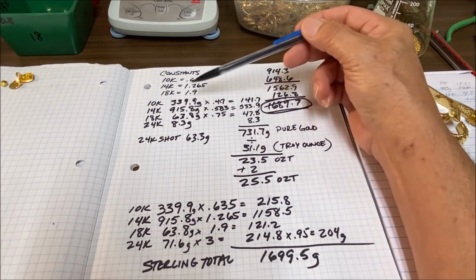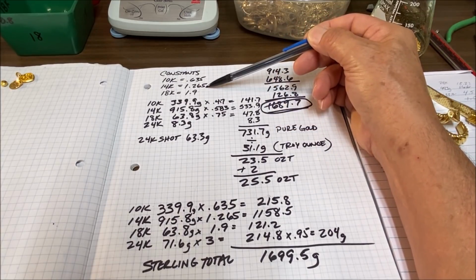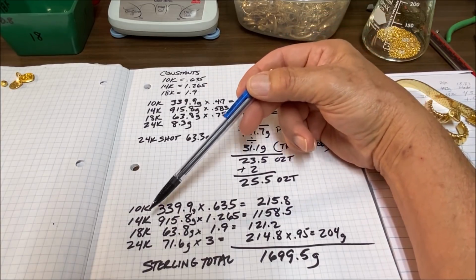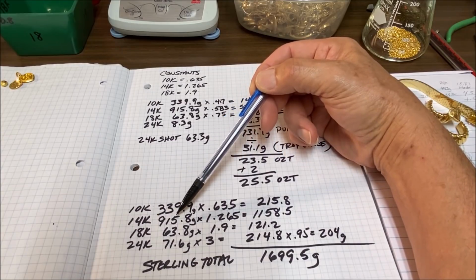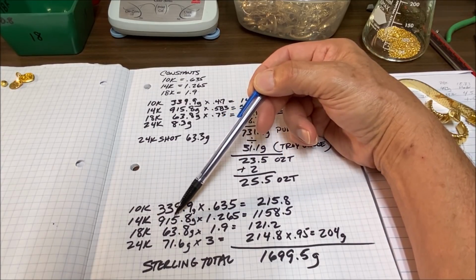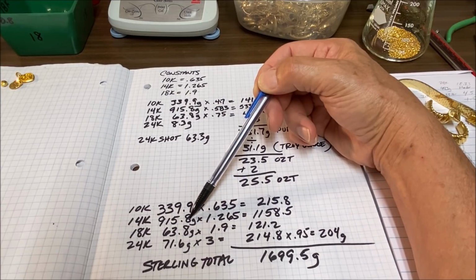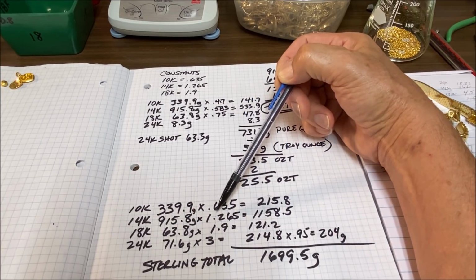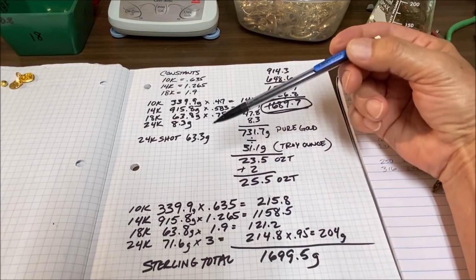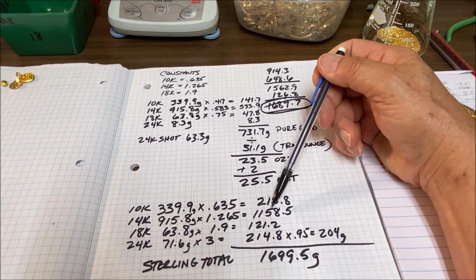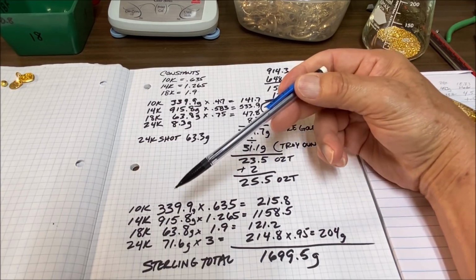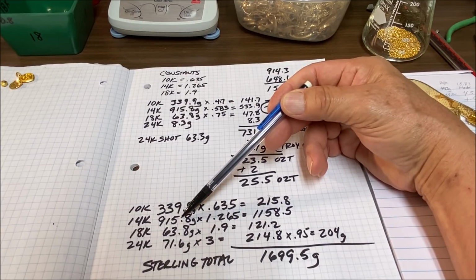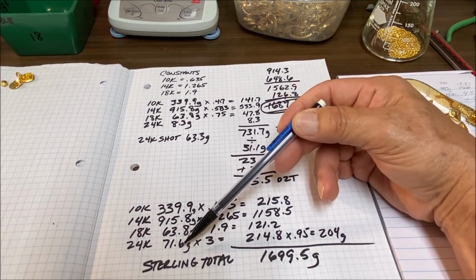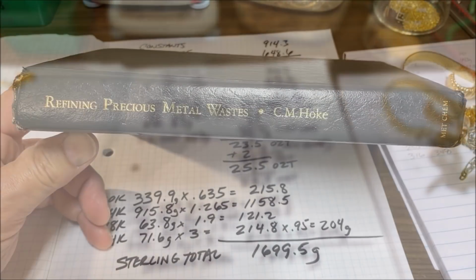14K, the constant is 1.265. And all I do is take the amount of 14K gold that I have, in this case it was 915.8 grams, multiply it by the constant, 1.265, and that tells me I need 1158.5 grams of sterling silver to properly inquart this amount of 14K gold, and so on down the list.